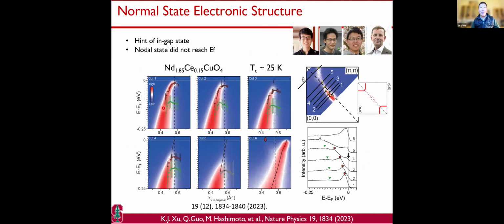You can see around 1, the band bends back near the Fermi level, bends back around the anti-ferromagnetic zone boundary. As you go from 1 to 2, this magnetic folded band, the folded gap, gets bigger and bigger, okay? And by the time it cuts number 5, that's where the hotspot is.